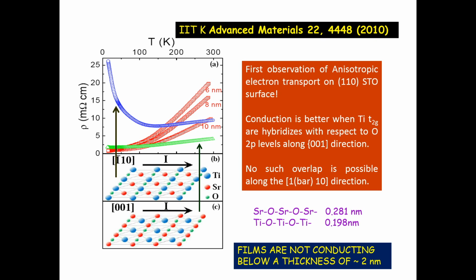One was 001 strontium titanate, which is isotropic in the plane, and the other 110, which is anisotropic. The 2 directions are not the same. The atomic coordination is not the same. And what we found was that on the isotropic 001 surface, this is 6 nanometer thick STO, this is 8, 10, all of them are metallic down to the lowest temperature that we could go, about 1.8 Kelvin in our PPMS.